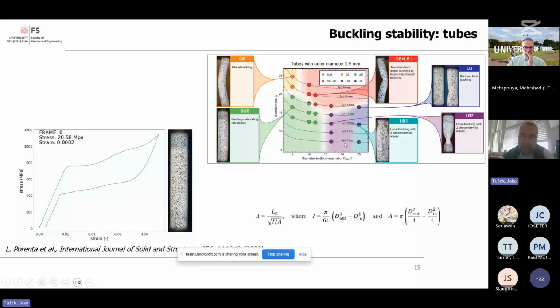If the tube is thick enough, so the diameter to thickness ratio is below 15, and if it's not too long, we observe this interesting buckling-unbuckling phenomenon. I have to show that here, because the tube starts to buckle, but then somewhere in the middle of the transformation plateau it straightens back, and a similar thing occurs upon unloading. So this tube actually didn't fail. It also has fatigue resistant operation, and it's thus functionally stable, but it shows this interesting phenomenon which is related to asymmetric martensitic transformation in the tube.